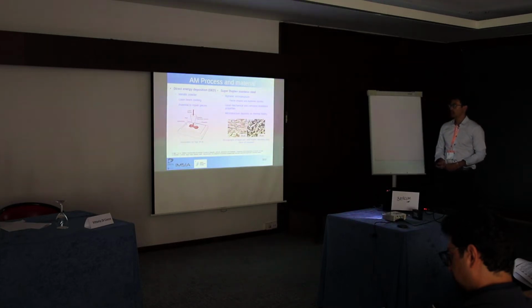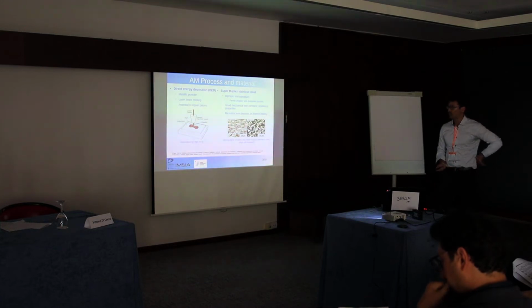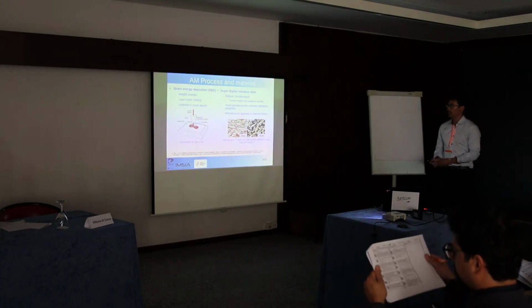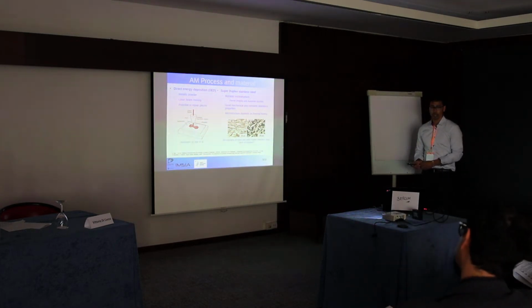So the couple here that we are studying is the laser direct energy deposition for the process, as well as the super duplex stainless steel for the material. This process works by expulsing powder through a nozzle here, while at the same time a laser melts the powder which is deposited on the printing surface. This allows to print either layer by layer, but also allows more complex applications such as repairing damaged pieces, for instance.